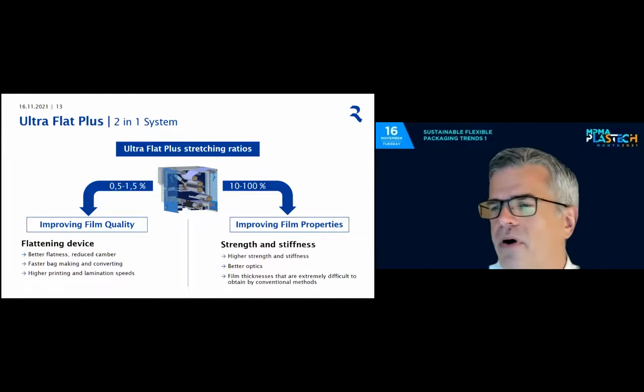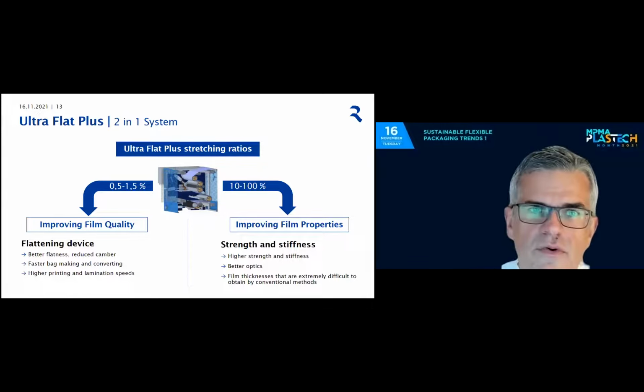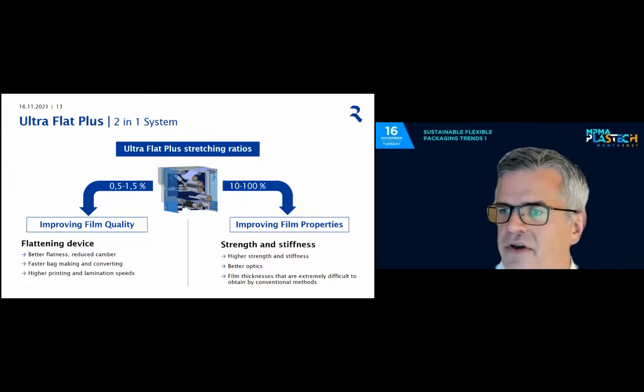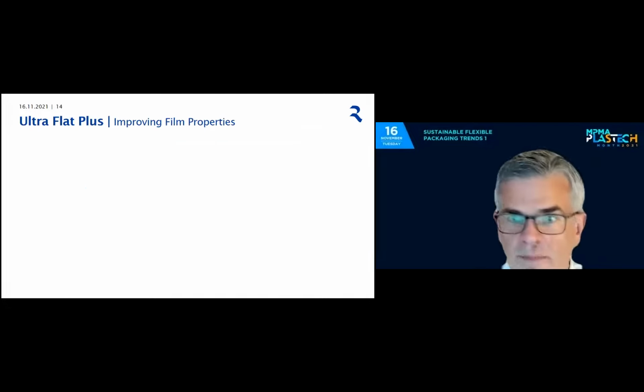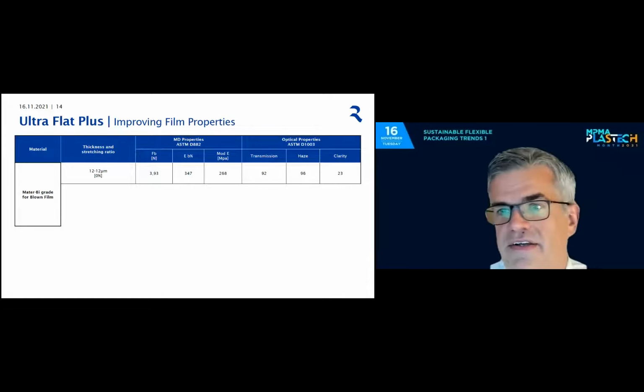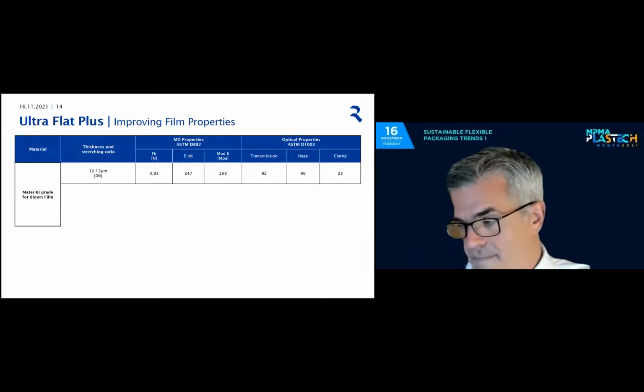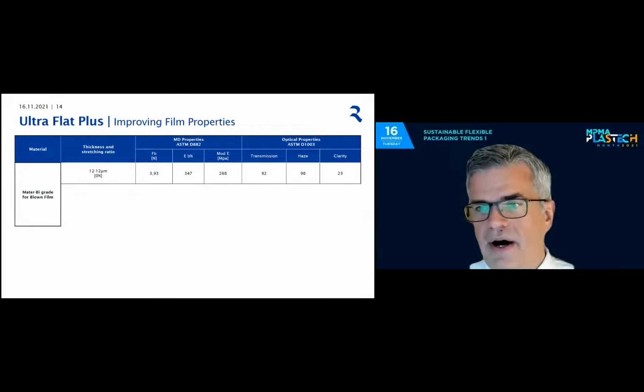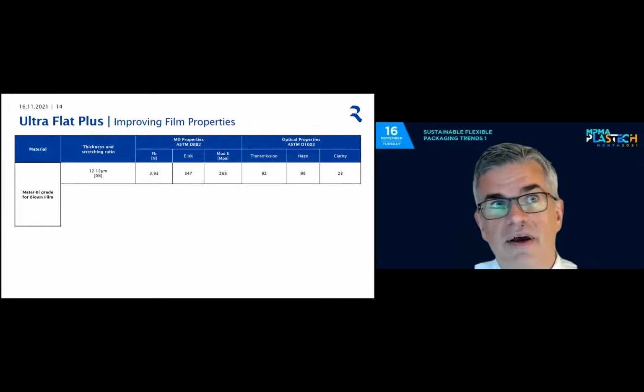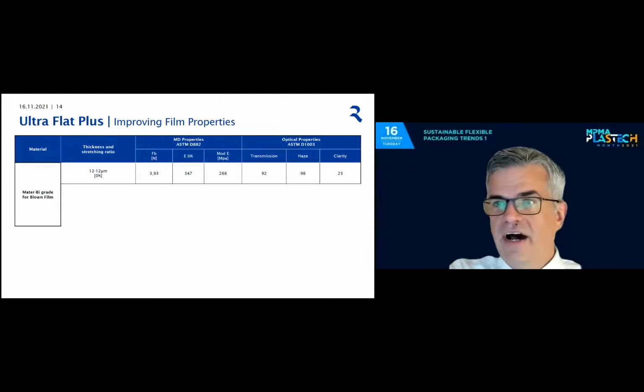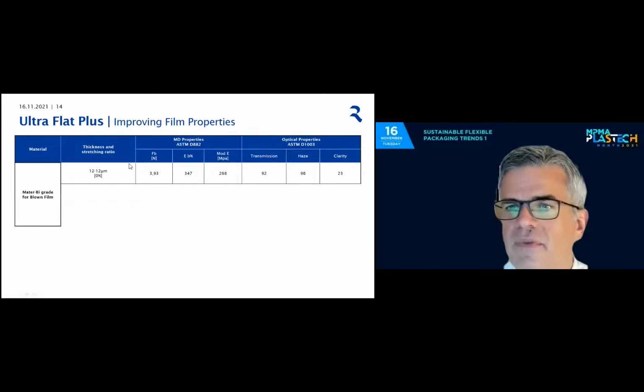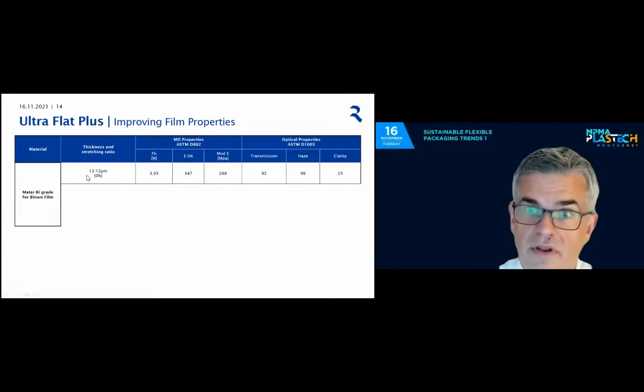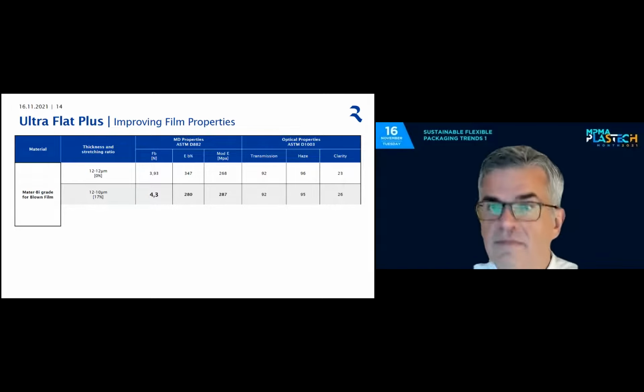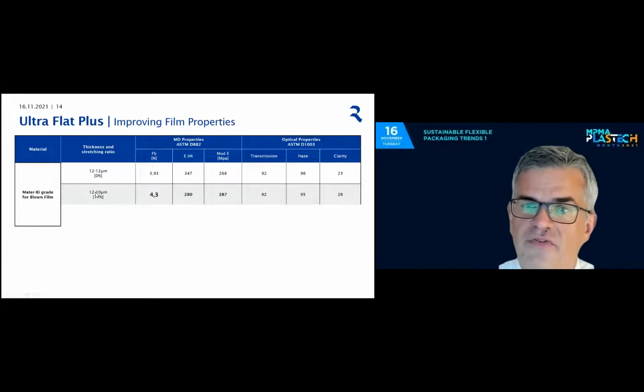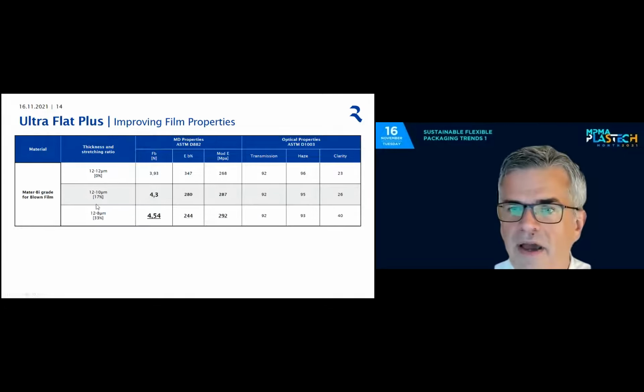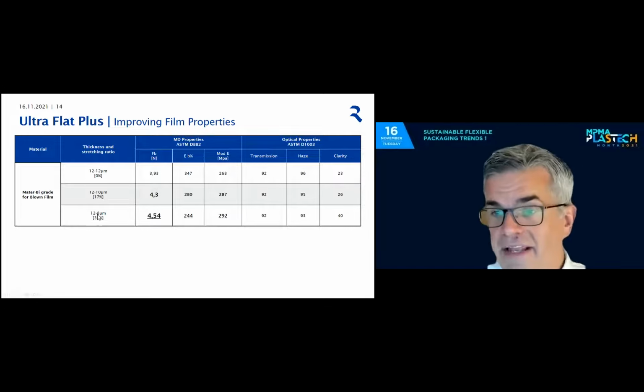But if you talk about biopolymers, it is really exciting to apply stretch between 10 and 100% to improve strength and stiffness. Because remember, the big disadvantage of those products, those bags for fruits in the supermarket, which are made of biopolymers, is the elongation under load. Please compare the numbers of the non-stretched 12 micron film with a film stretched from 12 to 10 microns, and a film stretched from 12 to 8 microns.